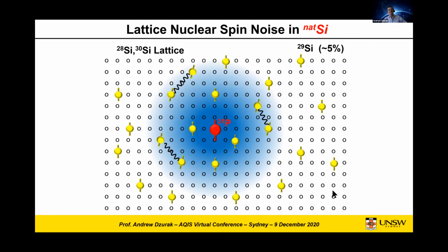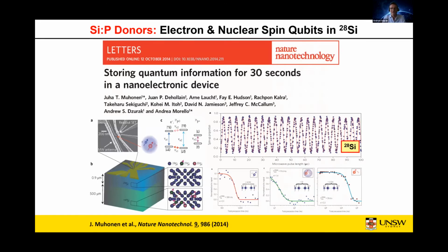The reason for that is that in naturally occurring silicon, around 5% of the nuclei are spin bearing. Most silicon atoms are silicon-28, which has 0 nuclear spin, but about 4.7% of them are silicon-29, which have a nuclear spin. These nuclei undergo flip-flop interactions, which fluctuate the local magnetic field, which then effectively causes decoherence of both the electron spin and the nuclear spin. It's particularly harmful to the electron spin. Fortunately, the solution is simply to isotopically enrich the silicon. This can be done using standard centrifuge techniques, or other laser-based purification techniques.